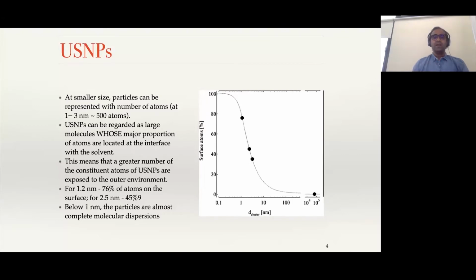Okay. Now, somebody would say, so what is the big deal? Why would you want a higher percentage of atoms on the surface? Now, here comes the trick. Before I tell the trick, let me just read out one important stat. For example, for a 1.2 nanometer particle, 76% of the atoms are on the surface. Now, if you increase that size from 1.2 nanometer to 2.5 nanometer, you see a drop in the percentage of atoms on the surface, and that goes to 45%.